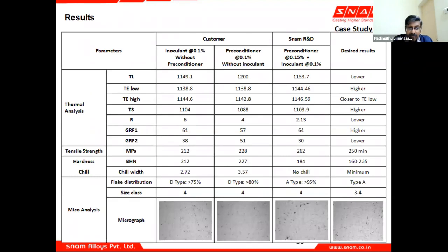So at the customer end, we did just the inoculant the way they were using, and then we were allowed to try just the preconditioner. In both cases, we found predominantly type D. When we added the preconditioner and the inoculant, we found a tremendous change in the metal quality, and there were no chills. The flake distribution had type A at 95%, and the micrographs are presented here.